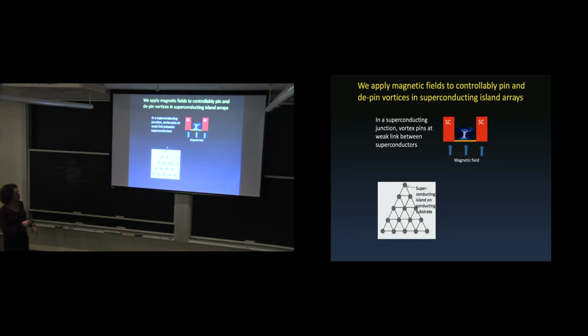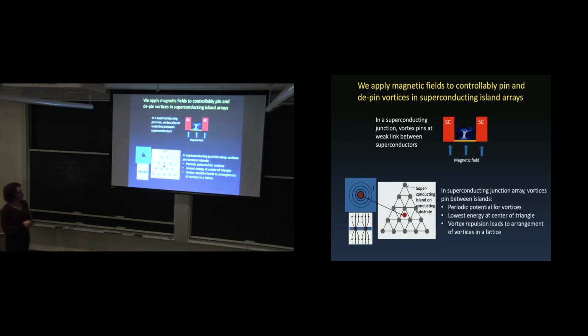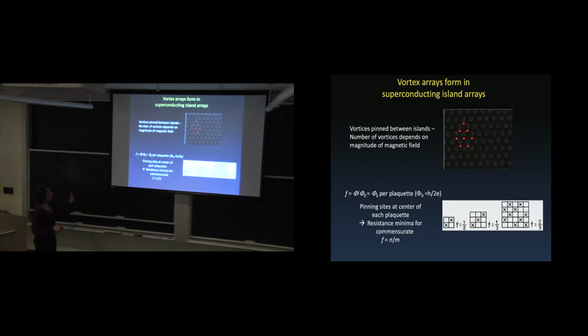So if we have superconducting islands, here's a triangular array of islands, the vortices will pin right in between where the islands are, which is the weakest point, and they penetrate all the way through. And so the array is basically a periodic potential for the vortices, where vortex repulsion makes the vortices arrange themselves into the lattice between the islands. Okay, so it's another picture. The red dots are vortices. They're in the lattice. Okay, but this is more interesting. So when they arrange themselves, they actually arrange themselves in an interesting sort of array, which means that, imagine if I have a square lattice and I apply just enough magnetic field that I can have one vortex in every other lattice point between my islands. Okay, that's a function of field.